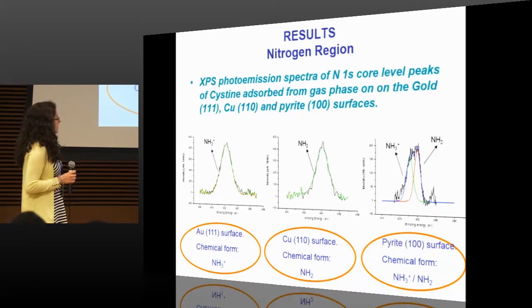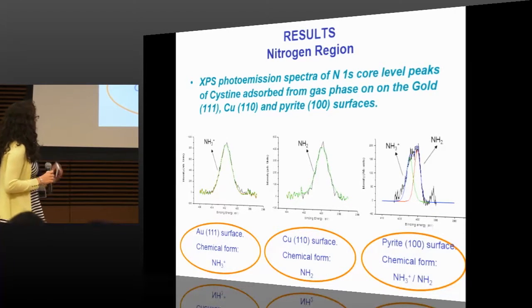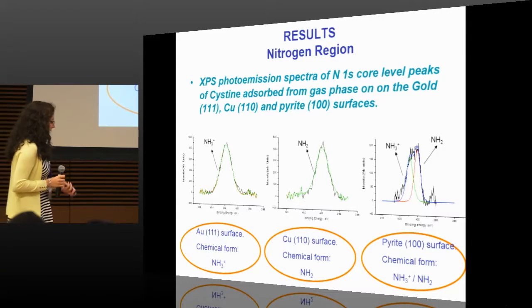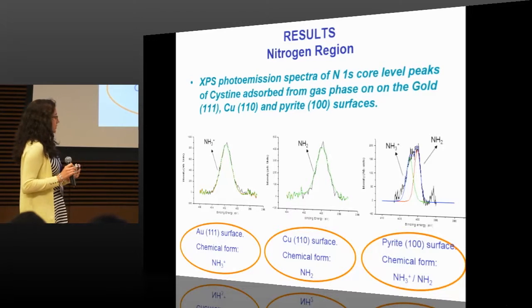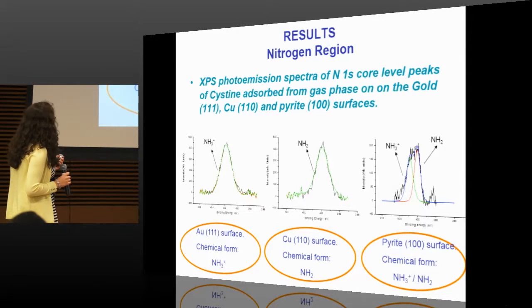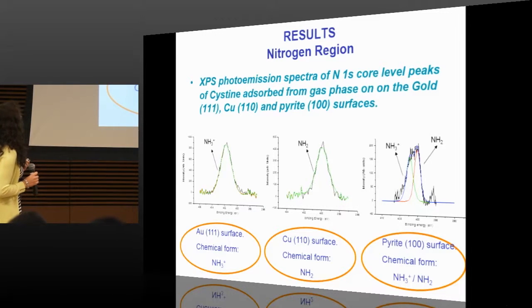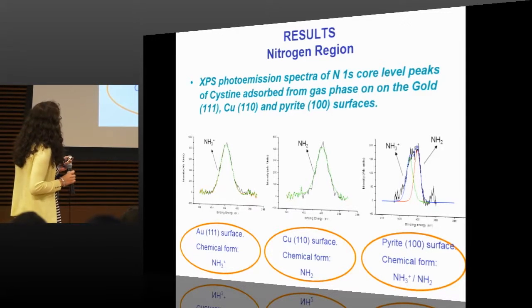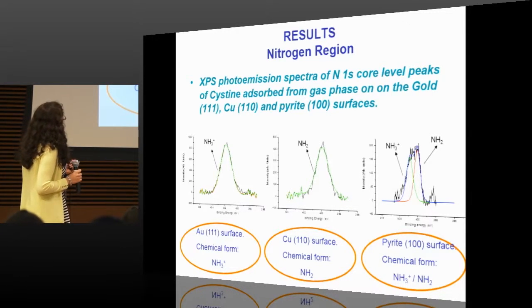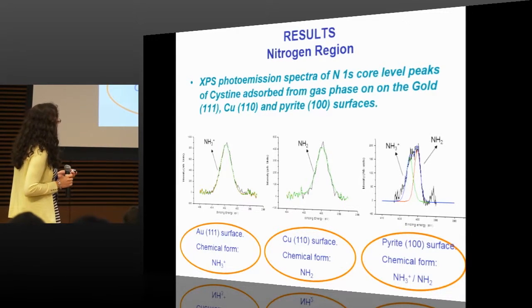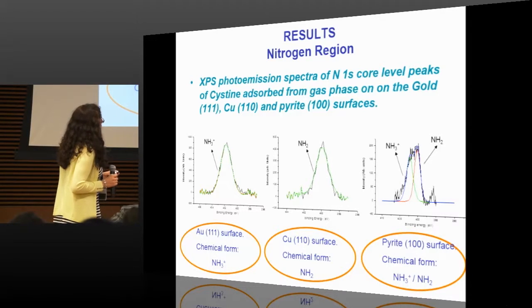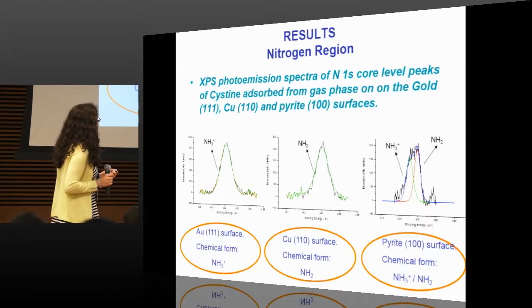And about the nitrogen region, we observe difference between the surfaces. When the amino acids are absorbed on the gold surface, we have only one component, and it's the protonated amino group. When the amino acid is absorbed on a copper surface, we have only one component, and it is the amino group. And on pyrite, we can observe both components, the amino group and the protonated amino group.